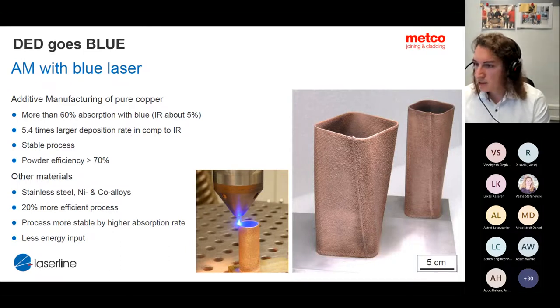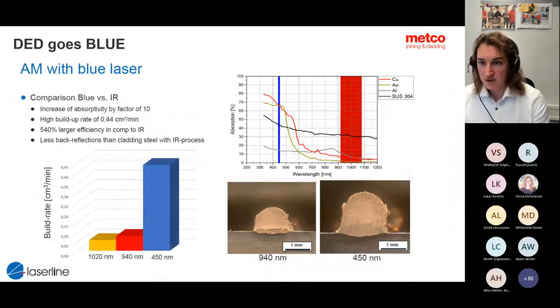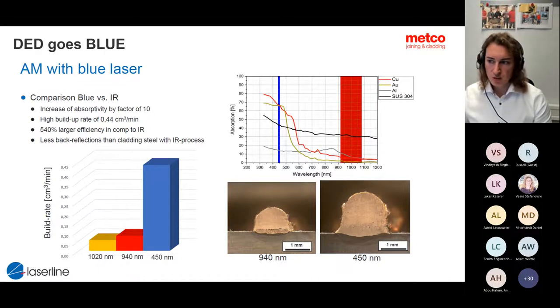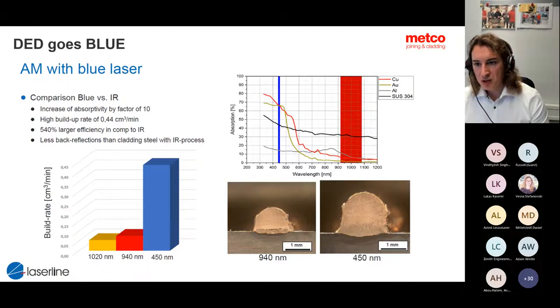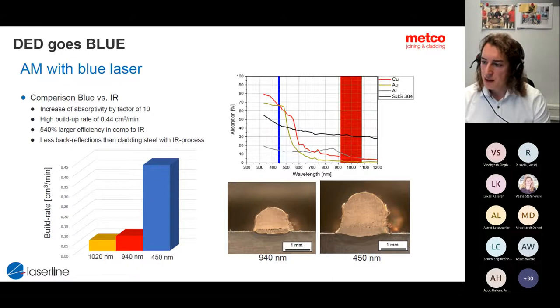Now we have it. So in 2022, Laserline introduced a 3 kilowatt laser, which helps you to build 3D components using blue. Why is it so important? If you work with pure copper, for example, you get extremely low absorption, and by changing the wavelength to blue, you are able to increase the absorption factor by a factor of 10. With 3 kilowatts, which is absolutely enough for building 3D components, you are able to achieve much better results, not only in terms of productivity, but also in terms of high quality.